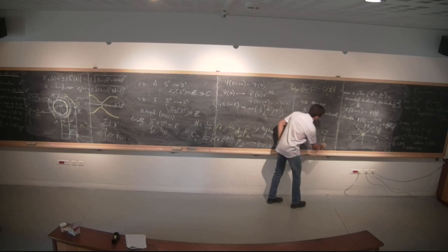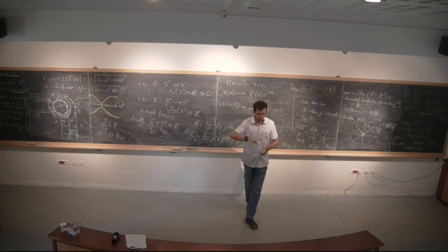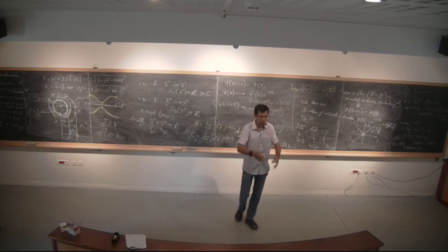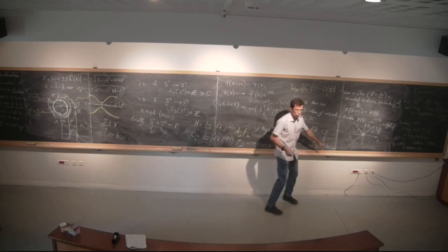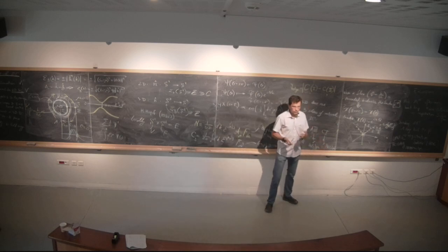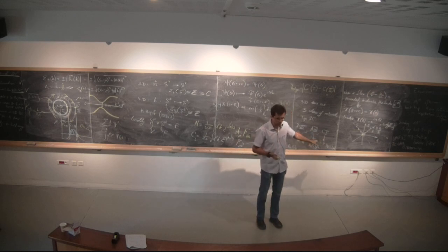This one has to have SU2 symmetry, which is an even easier task. That means forget about all the heavy elements, maybe cuprates; you should focus on something that has relatively weak spin-orbit coupling, so spin is a good quantum number. The requirement, as usual, is that it has to be fully gapped in 3 dimensions. Cuprates are not, they have lines of nodes. So the first task is to find a fully gapped superconductor.